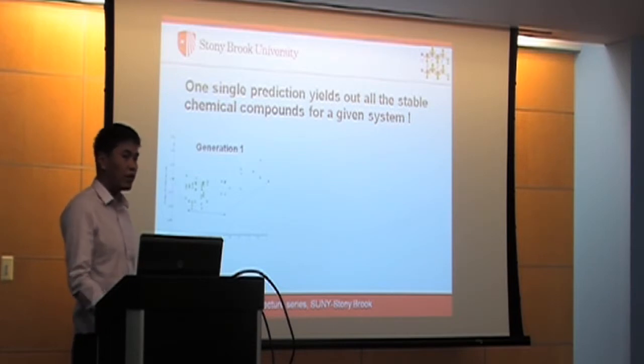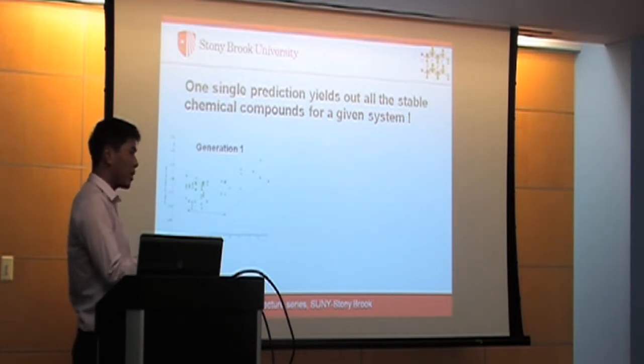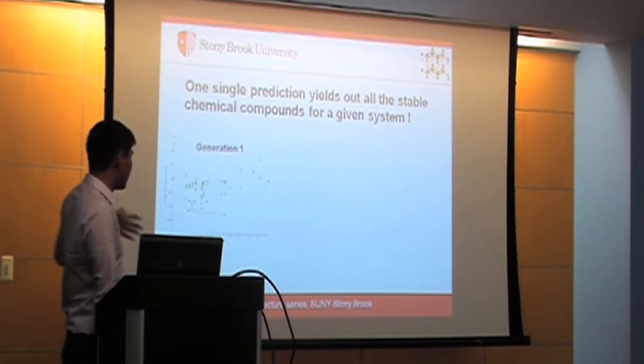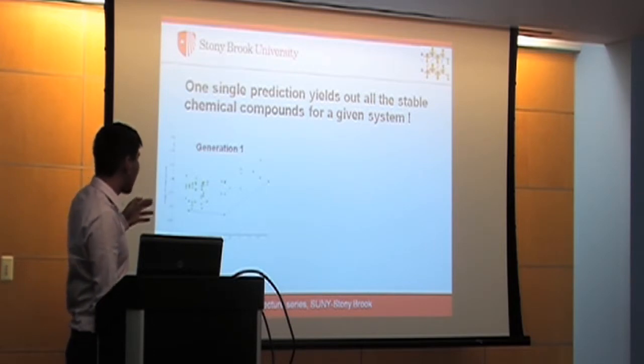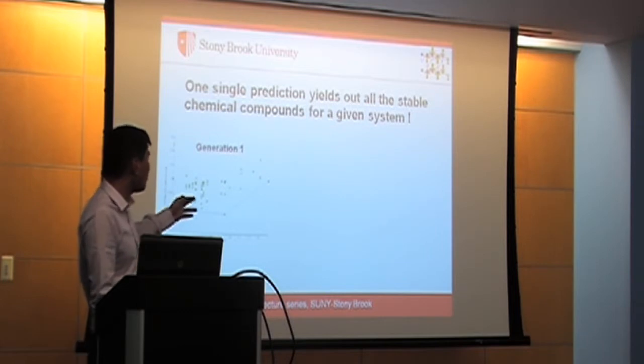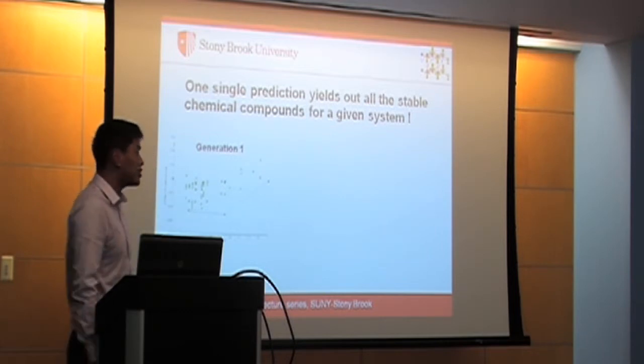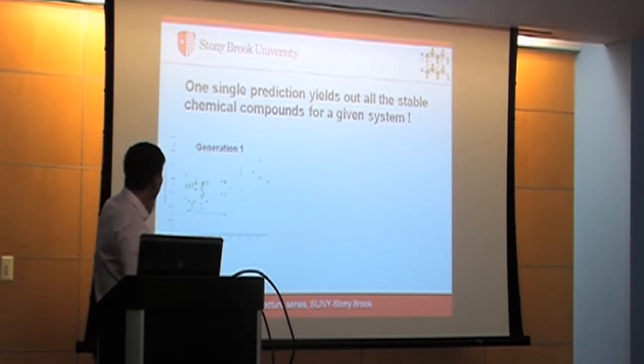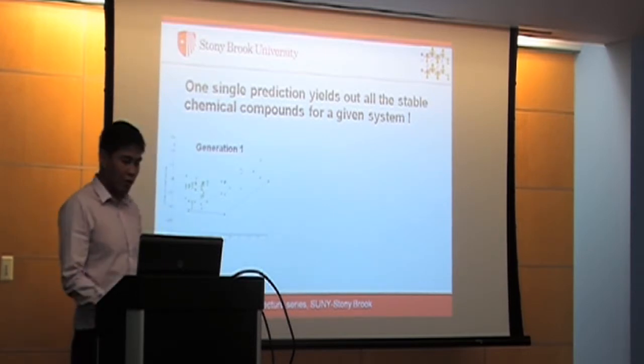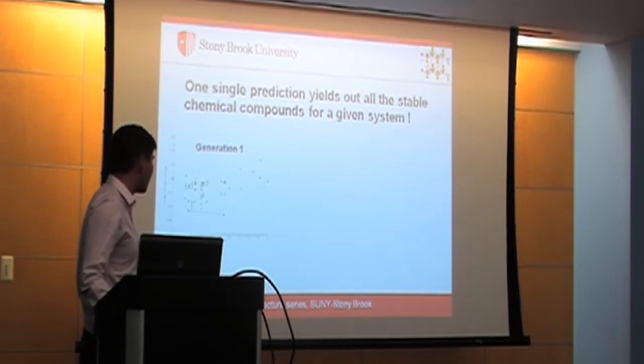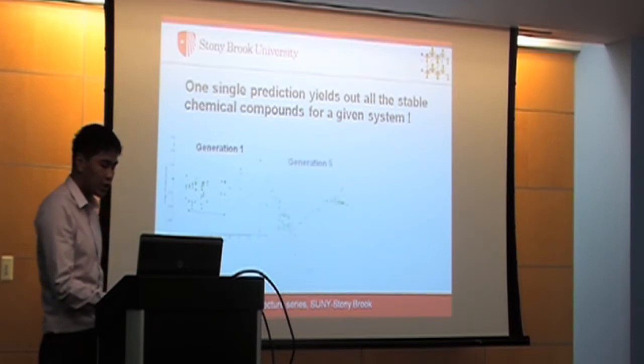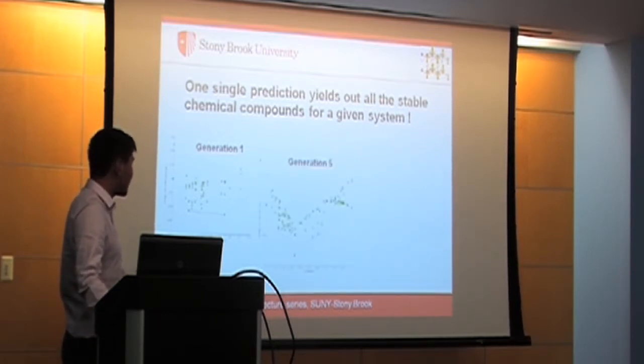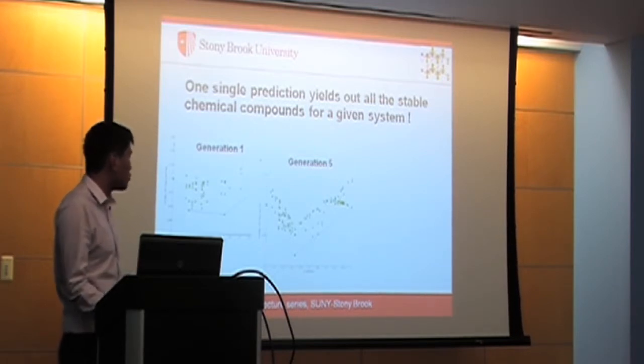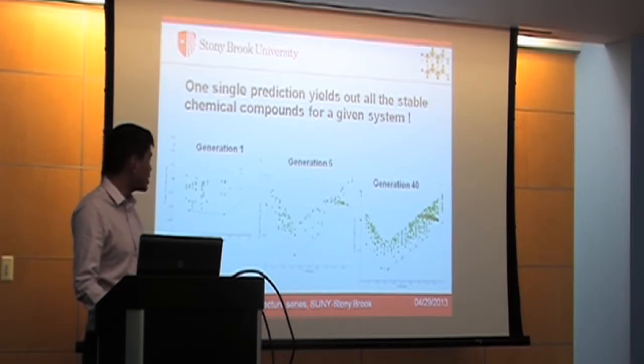So it works in such a way. Firstly, we generate structures from random chemical compositions, and then we analyze these energy scatter plots, and then we can get such a convex hull. And then we evaluate the fitness function of these structures by the distance from the energy scatter to the nearest convex hull. So that we can move on to the selection process, and then we use these structures as parents to generate new structures, so that we can gradually establish the convex hull and optimize it until we can find the right ground state and the right solution.